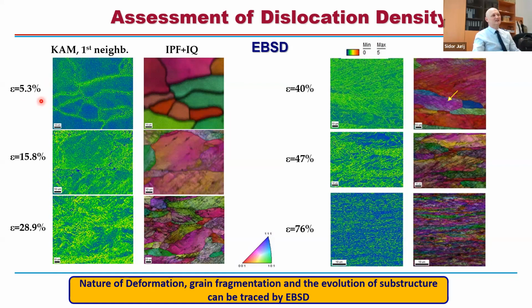And what was very interesting to observe is that at low thickness reductions, they in fact move towards the grain boundaries, and they are located along the grain boundaries. And the more you increase the level of straining, the more homogeneous dislocation distribution you observe. And then you observe evolution of cells at higher straining levels, which you can see here. So the nature of deformation, grain fragmentation, and the evolution of substructure can be nicely traced by the electron backscatter diffraction technique.